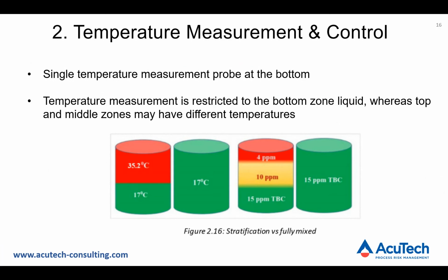As can be seen in those figures, the first figure indicates that even though the bottom temperature might indicate 17 degrees centigrade, the top layer could be at around 35 degrees centigrade, wherein the polymerization can initiate. This also causes issues with respect to the TBC content. If the temperature is around 17 degrees centigrade, the TBC content, which is expected to be maintained at 15 ppm, would remain uniform throughout the storage tank. But if there is a higher temperature on the top layer, then certainly the TBC inhibitor content would also reduce periodically. This poor mixing due to the modification, inappropriate temperature measurement, and lack of auto temperature control system must have led to the thermal stratification in the tank.